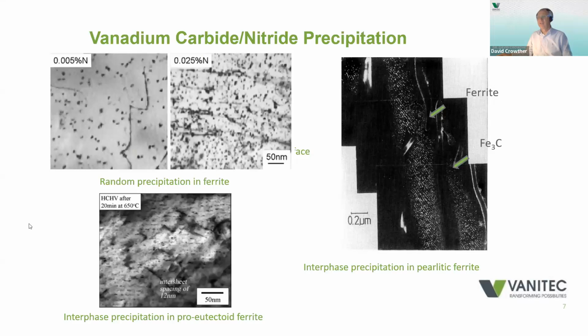In the top two pictures, we can see a random distribution of precipitates, and you can see some nice interactions of precipitates and dislocations. On the right-hand side, you can see a much denser precipitate distribution, and this is due to the high nitrogen content. And you'll often see vanadium used in combination with high nitrogen. In the bottom, we can see rows of vanadium precipitates, and this is known as interphase precipitation, and again, a common type of vanadium precipitate distribution.